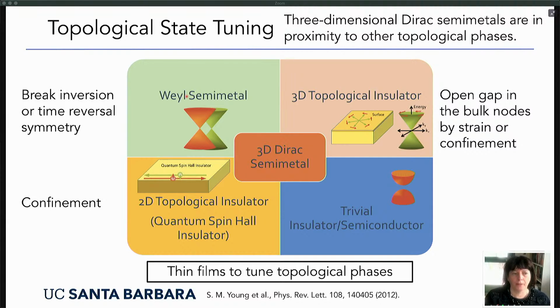If you take this 3D topological insulator state and make this very, very thin, the predictions, and this has not been shown to my knowledge, are that you should actually then end up with a two-dimensional topological insulator that, without any application of a magnetic field, has edge states somewhat similar to the edge states in a quantum Hall effect, but without a magnetic field. Okay, so what you also see from this is that thin films should be very interesting because in thin films we can break these symmetries, and of course in thin films we can make thin things.